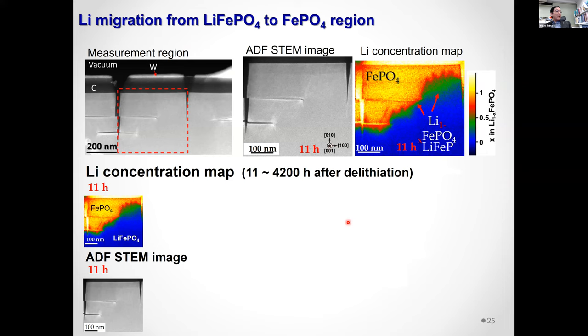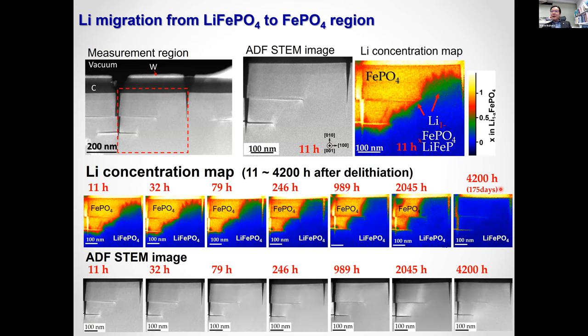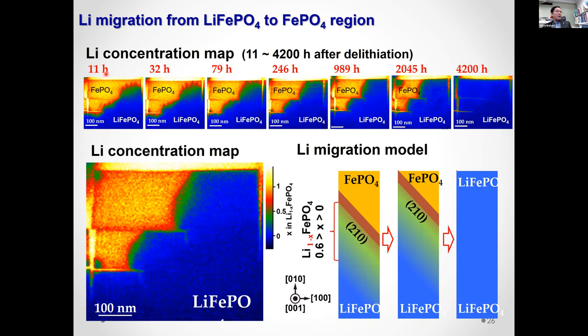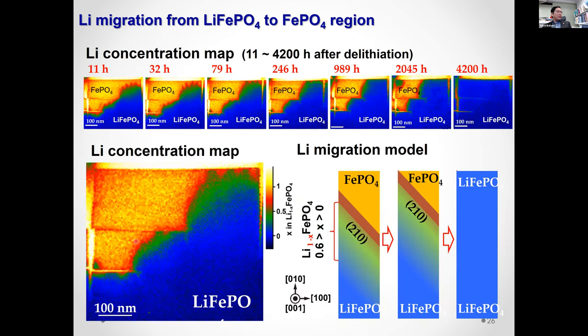And my student was very patient. He observed this region from 11 hours to almost half a year later. So in half a year, at 4,200 hours, LiFePO4 is completely recovered. So the lithium has diffused out like that. From 11 hours to 4,200 hours, he made a movie.